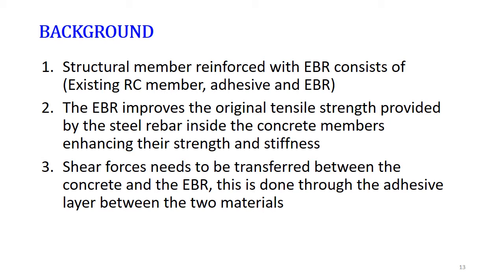Of course, in order to do that, there must be some kind of shear transfer between the externally bonded material and the element that you want to strengthen. And there is usually an adhesive or epoxy adhesive, a layer in between the two of them. So the shear strength in between the two needs to be evaluated in order to ensure the effectiveness of the strengthening.